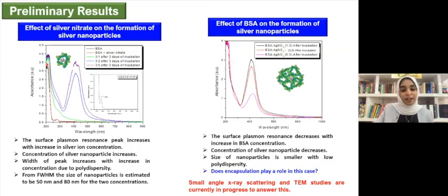So here are our preliminary results. I can see here that on the left-hand side, we looked at the effect of silver nitrate on the formation of our silver nanoparticles. So we used the UV-Vis spectrometer here again and varied the concentration of our silver nitrate, and we kept the concentration of our BSA constant. And here we observed that as we increased the concentration of our silver nitrate, the surface plasmon resonance peak also increased with that. And so we got a higher concentration of our silver nanoparticles.